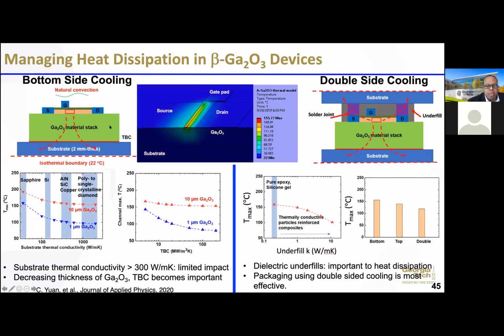And this gets into, all right, can you just simply take gallium oxide and put it on top of diamond and cool it like we're doing with gallium nitride? Well, the answer is yes and no. If I have a very thick layer of gallium oxide, the majority of my thermal resistance comes from the gallium oxide, and it really doesn't matter what I put down here because this is going to cause the thermal resistance, which is going to raise my temperature. But if I make it really thin, you can see that as I make it thinner, then the substrate thermal conductivity comes into play. So that's the structure that we saw mostly with gallium nitride.